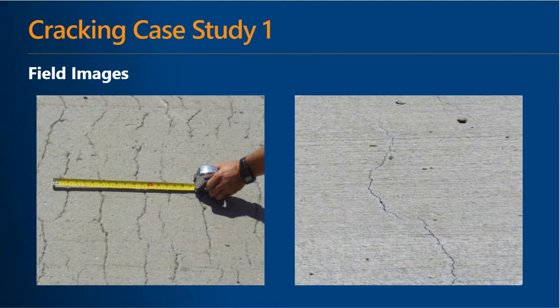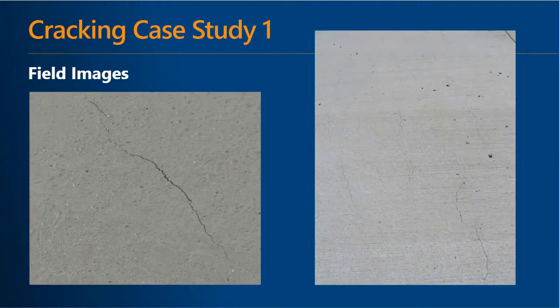And so some examples of what you may see in the field are shown. There's a parallel nature of these cracks on the left-hand image with a fairly regular spacing. There's a discontinuity that you may see in the cracks that you can see on the right. Again, you can see a discontinuity and a parallel alignment of cracking on the right image. And on the left, you may even start seeing some tear-like features. At this point, if a petrographer was in the field, or if you were to send us pictures similar to this from the field, we would start thinking about early age crack mechanisms.